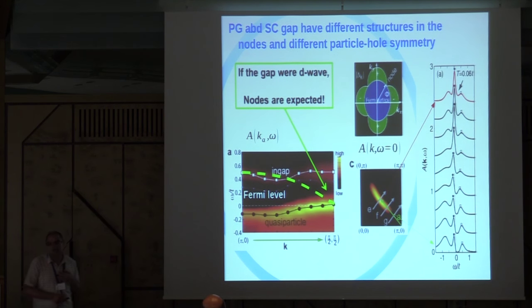And so we say, well, many theories are based on the fact that the pseudogap has a similar shape. Now, let's look at our pseudogap going from the antinode to the node. So from the antinode to the node, and this is the energy axis. So it's like ARPES a bit. And you see that this is a quasi-particle band that touches the Fermi level in the nodal point. And the pseudogap is this darker region. And you see that there is a parallel, more faint band that runs at positive energies. And the pseudogap is always there, actually.